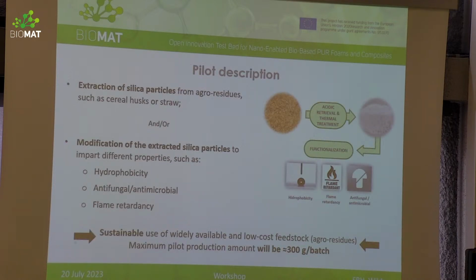So what do we do at Senti's pilot line? Our target is to sustainably use widely available and low-cost feedstocks, such as agro-residues, to extract silica particles and then modify them to impart different properties of interest, such as hydrophobicity, antimicrobial resistance, and flame retardancy. The maximum pilot production amount is on average approximately 300 grams per batch.